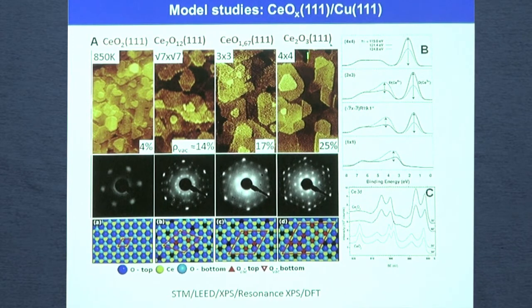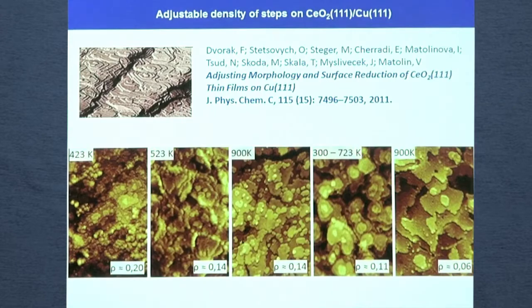You can see the example here. For example, this is Ce2O3, which is fully reduced, to the second stable structure, which is in this case the cubic structure. We are controlling stoichiometry by XPS, but also by resonance spectroscopy at synchrotron. I will explain later how it works. We can see by electron diffraction the different reconstructions corresponding to different degrees of reduction, but still single crystalline. And we can also perform DFT calculations, comparing the results of theory and experiments.